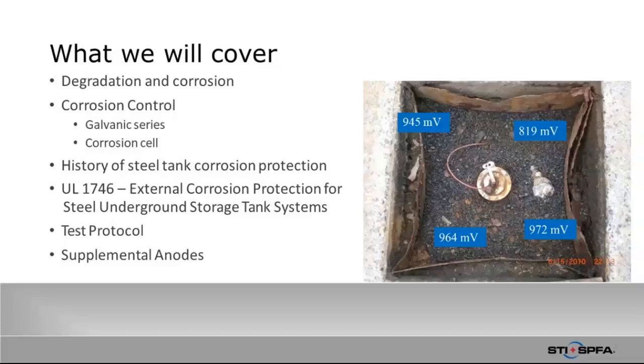If they need the tank to fail, you can find a spot like you see in a few of these spots. They're a little low. One spot is. There's also places that pass. If you want to pass a tank, you can certainly find some other galvanized material that can give some readings that aren't quite as accurate for cathodic protection as you'd want. And I'll hit on how to get around that issue in a little bit.